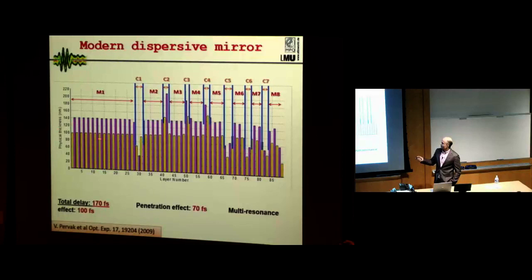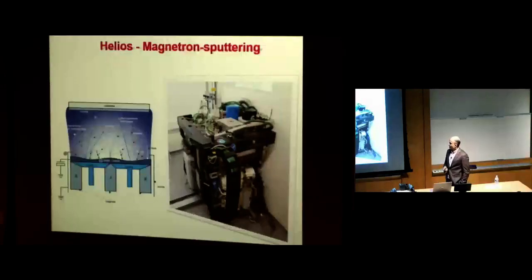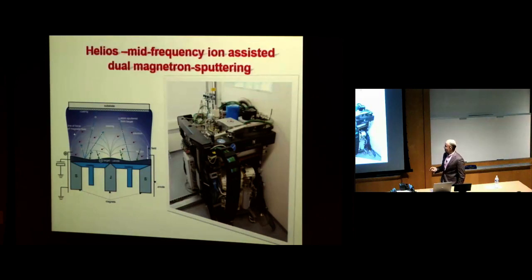You can see that some layers are about 100 nanometers, some are much thinner, but if one of these layers, instead of 100 nanometers as designed, will be 101 nanometers, the whole structure will not work anymore. It means we have to provide very great precision, and we have a few coating machines in our facility. The first is called magnetron sputtering machines. Basically, the principle of how it works is shown here. But before going to the basics, I should say that magnetron sputtering is not the full name, actually.